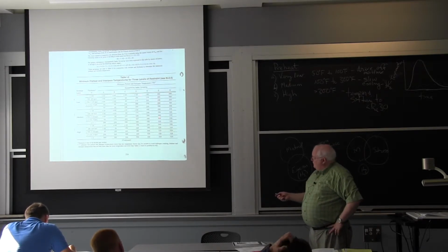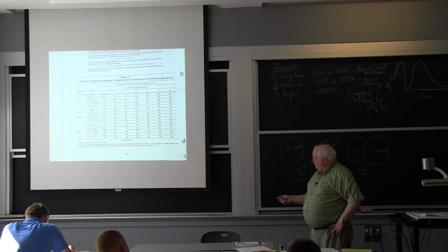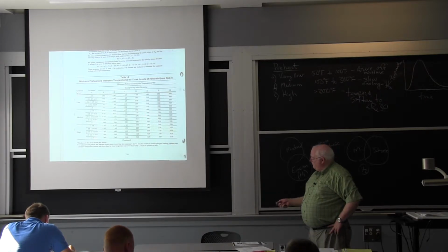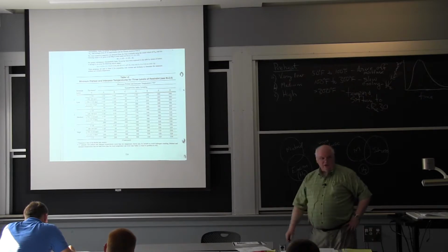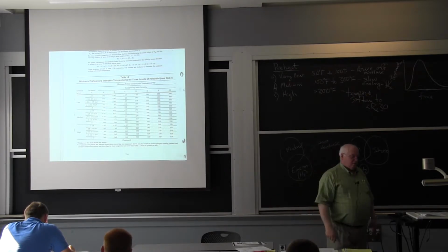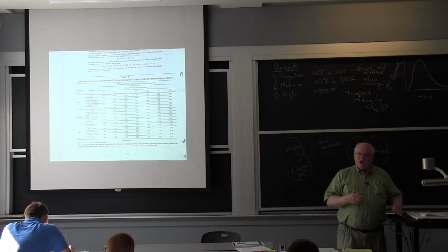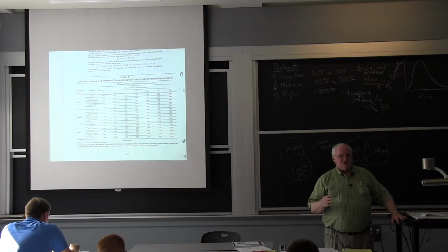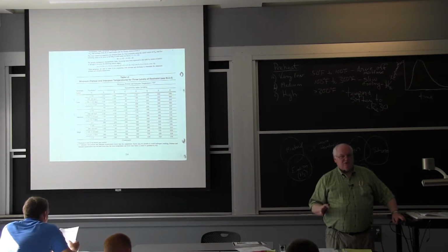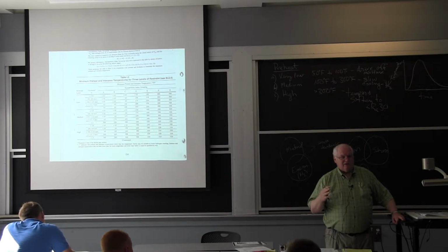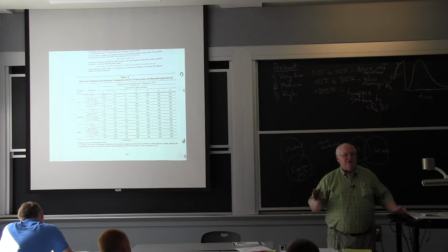Usually it's only in the D and F where you're starting to get the fairly high preheat, but if you have high restraint and greater than 3 inches thick, it's always 240 to 300, even if you have very low carbon equivalent. So it's a complex function. There are many variables. This turns out to be the simplest, and it just took me 10 minutes to walk you through it, right? And if I was giving quizzes, this would be the perfect quiz question.